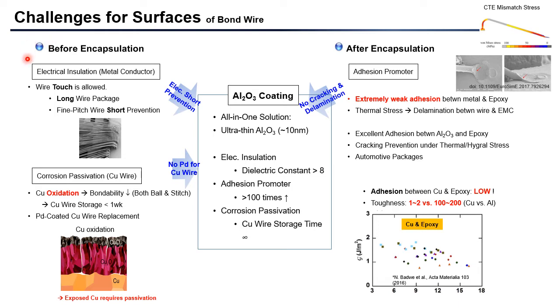Before encapsulation, metal bond wire does not provide electrical insulation. Metal wires do not provide a corrosion passivation. After encapsulation, metal wire does not provide a good adhesion to epoxy molding compound. On the other hand, aluminum oxide coating can provide electrical insulation, corrosion passivation, and good adhesion to EMC.